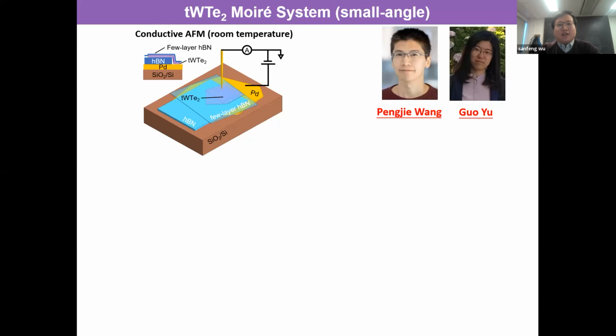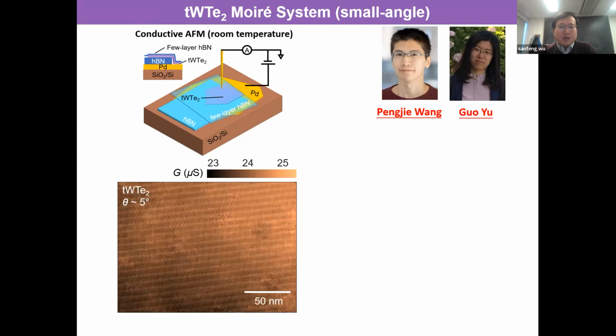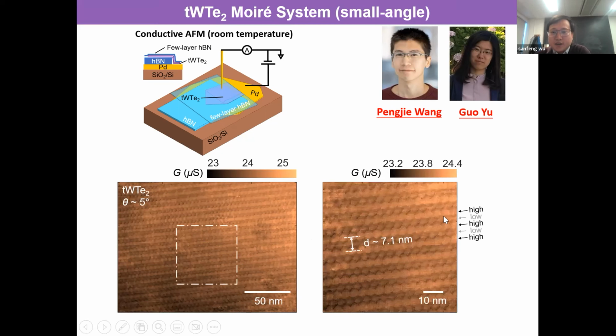Okay, so this is nothing but just like STM, but it's performed in the AFM machine at room temperature to check the Moiré system. That's what they find. You can already see the patterns that are very similar to what I have drawn for you in PowerPoint. Right? So you can zoom in here. They aim at 5 degrees, end up with 7.1 nanometer distance. I told you it should be 7.2. It's very close. And you can see the rectangular unit cell.